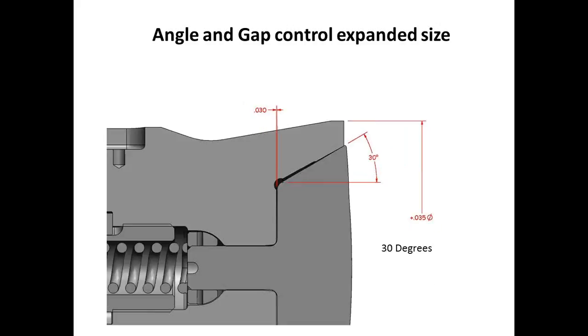If we take the same dummy block and we use a 30-degree angle, the gap would be reduced to about 30 thou, which would limit us to about 35 thousandths of an inch expansion on diameter. And again, this is just mechanical and does not include thermal.